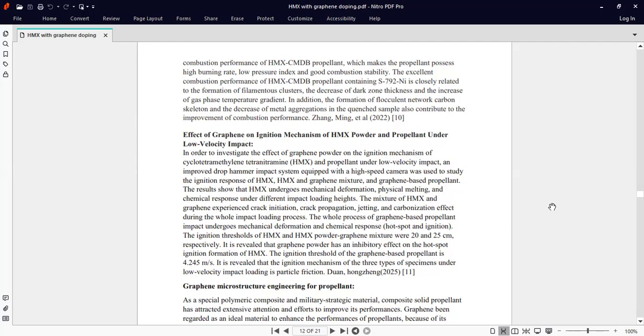Effect of graphene on the ignition mechanism of HMX powder and propellant under low velocity impact. In order to investigate the effect of graphene powder on the ignition mechanism of cyclotetramethylene tetranitramine, HMX, and propellant under low velocity impact, an improved drop hammer impact system equipped with a high speed camera was used to study the ignition response of HMX, the HMX and graphene mixture, and graphene-based propellant.